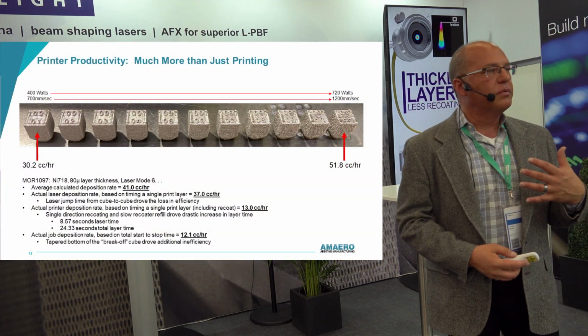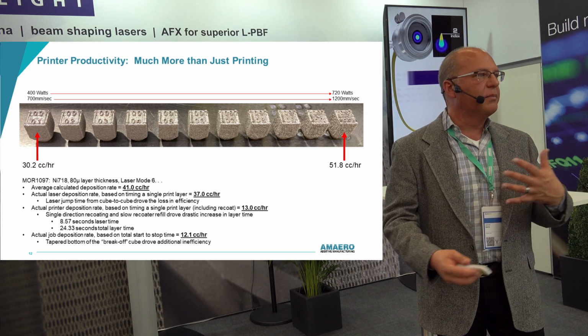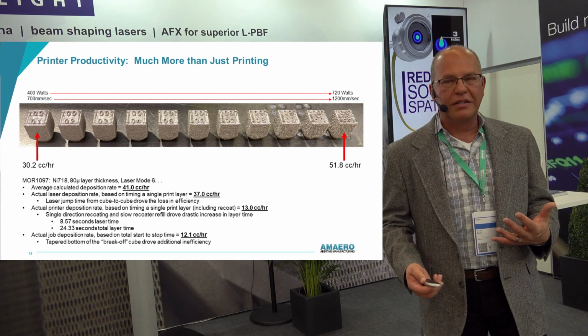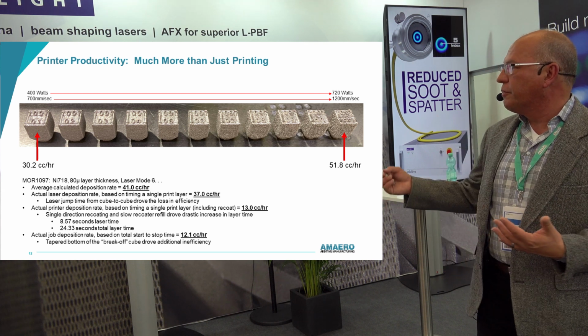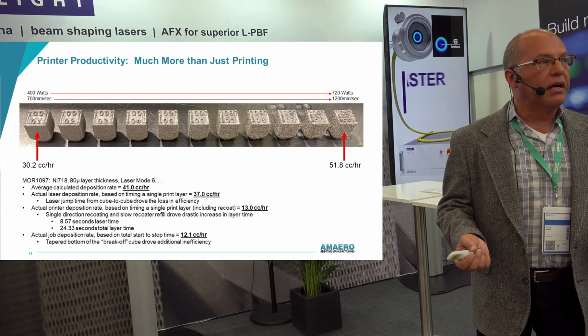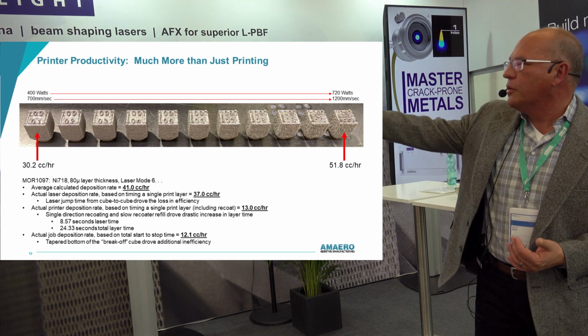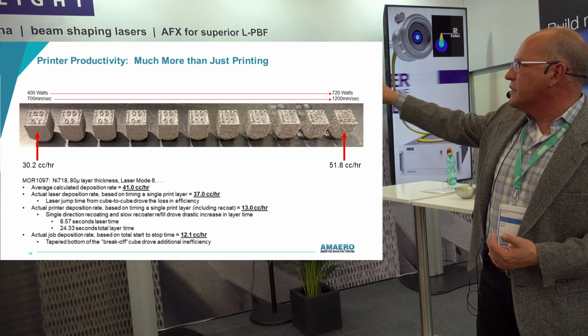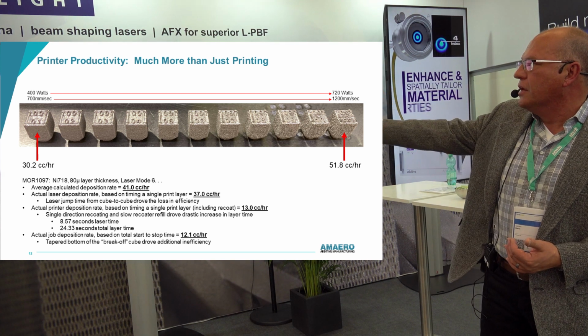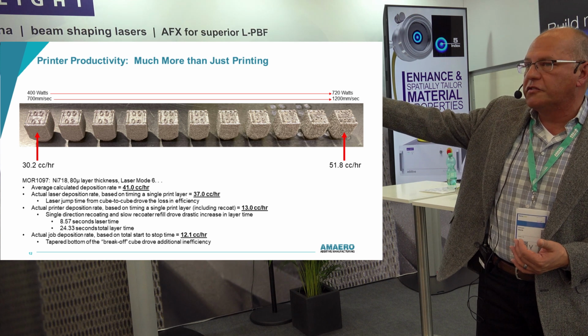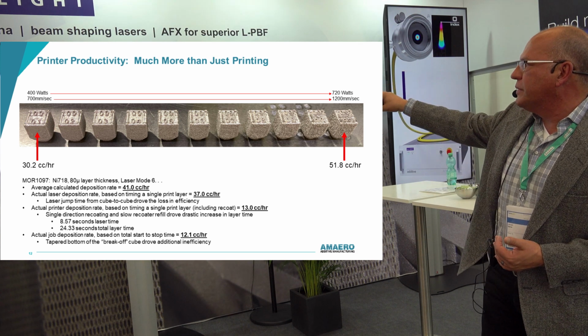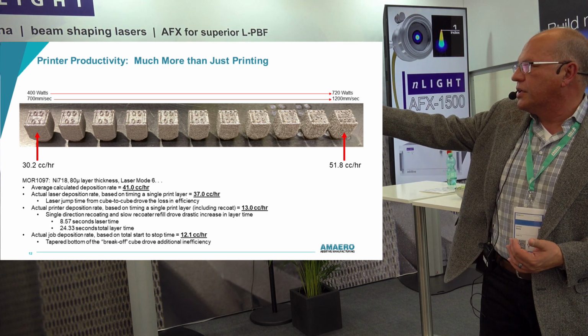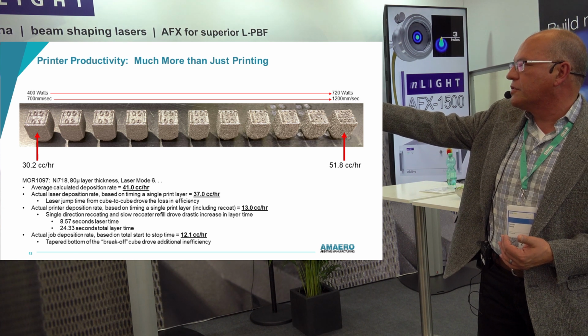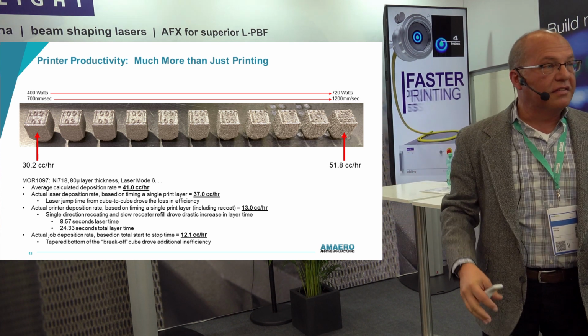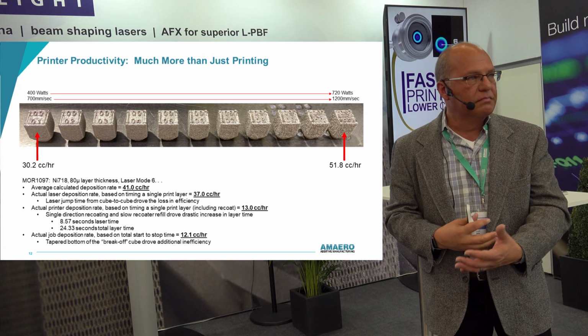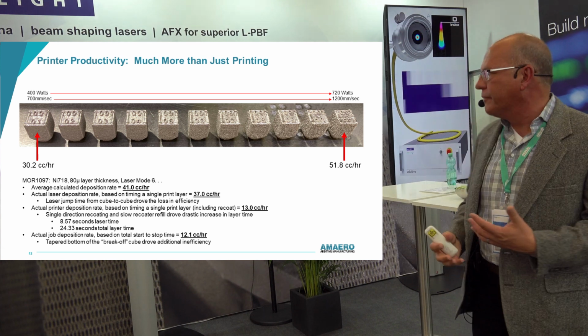I switched to 718 because it's a friendlier material, and I wanted to get crazier with all this printing. So here I'm printing 718 at 80 micron layers. In this particular DOE, the volumetric energy is the same for every one of those cubes, but we have low power, low speed on the left, high power, high speed on the right, and an increase in deposition rate from 30 cc's an hour to 51 cc's an hour. Again, like double the normal high deposition rate.